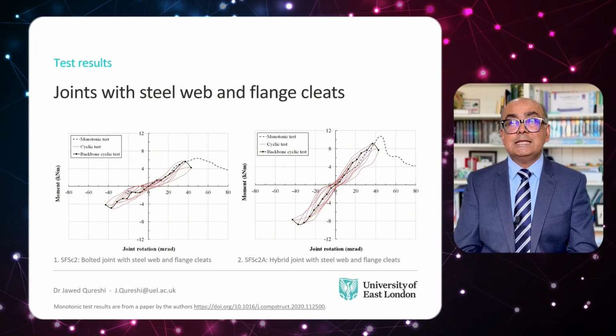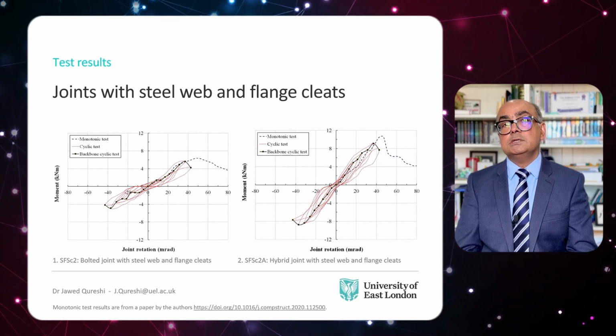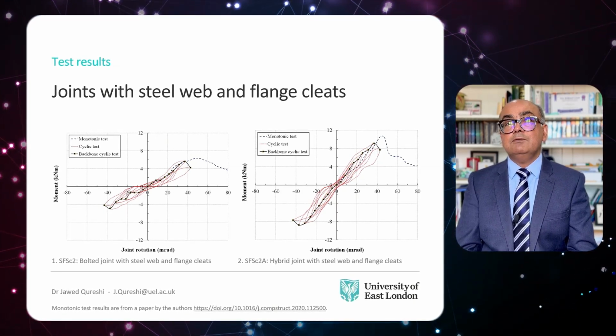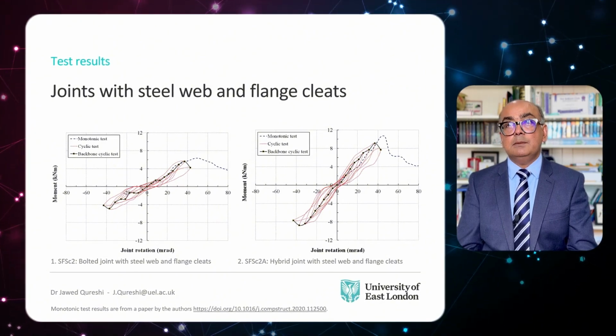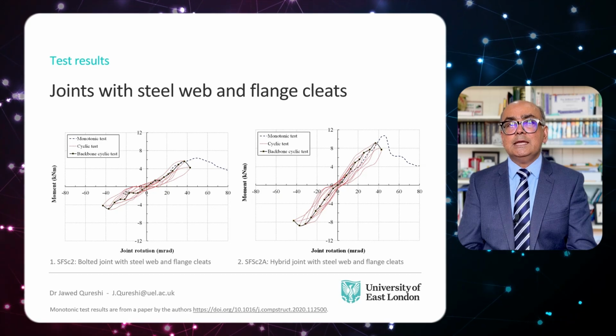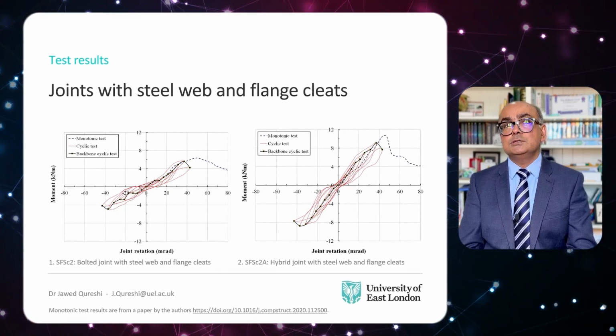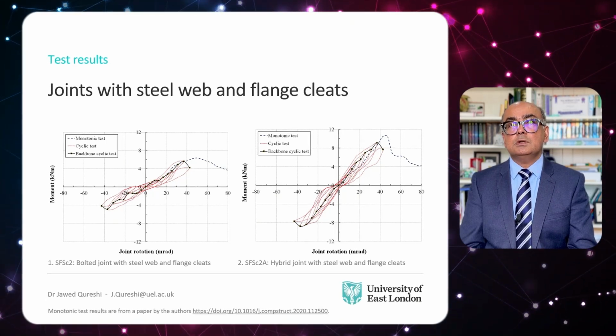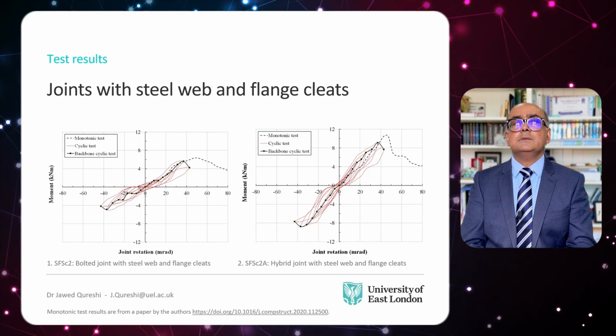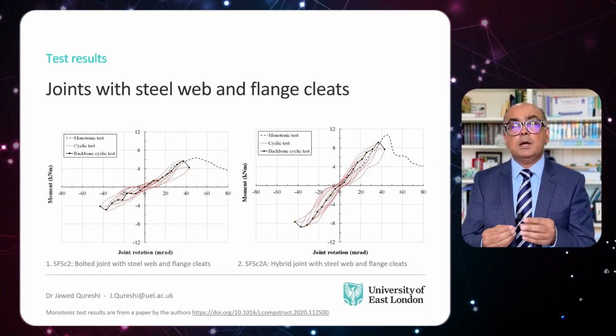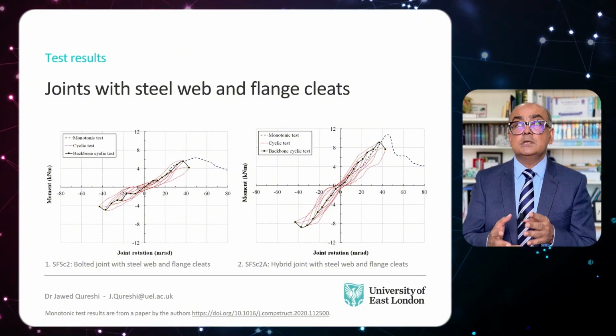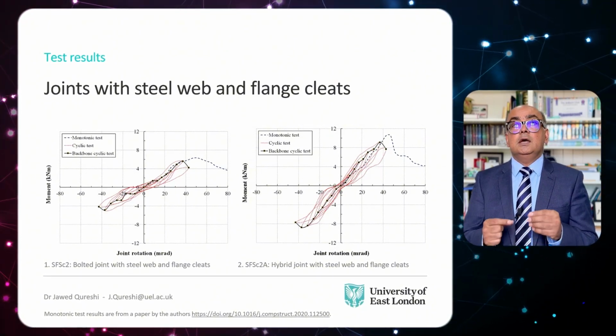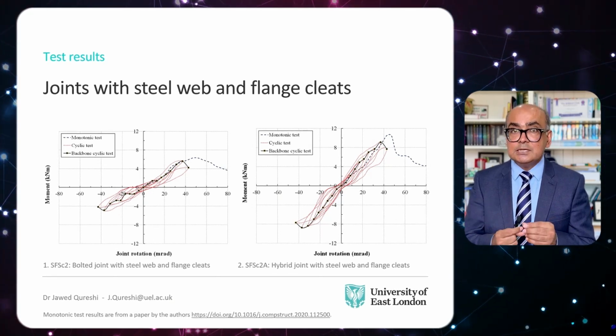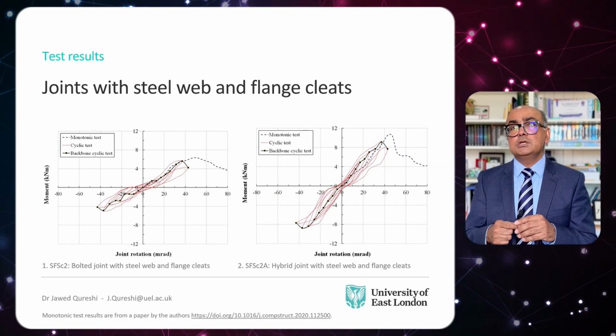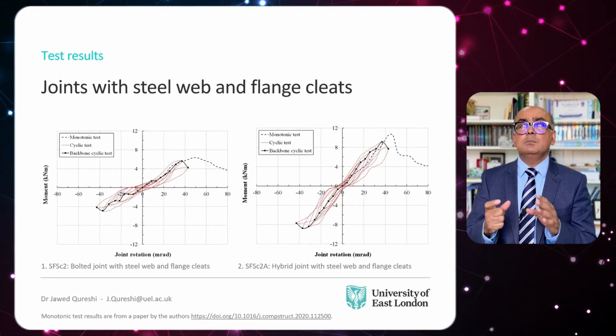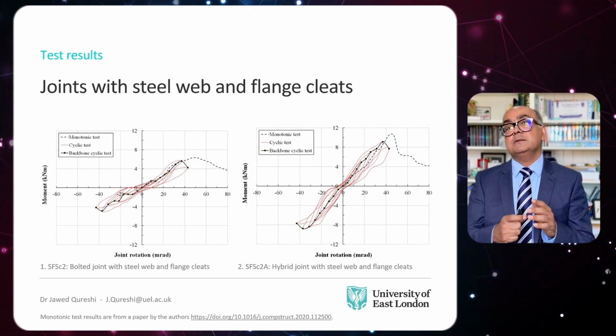Test results. Joints with steel web and flange cleats. These are moment rotation, hysteresis curves or loops. Left curve is for bolted joint and right curve is for hybrid joint. Monotonic curves are shown by dashed lines and cyclic curves are shown by dotted lines, and backbone curves by solid line with markers. It's interesting to note that bolted joints started to show damage at about 2 kN meter and hybrid joints showed damage at 5 kN meter. Hybrid joints certainly delayed initiation of damage. Hybrid joints showed at least 50% higher moment and stiffness than companion bolted joints.